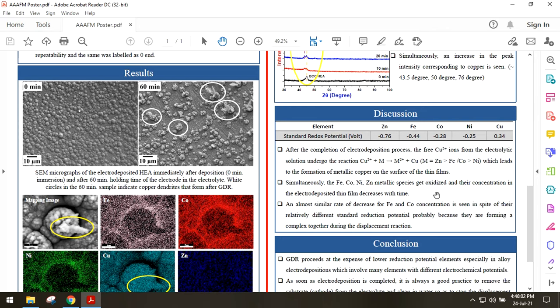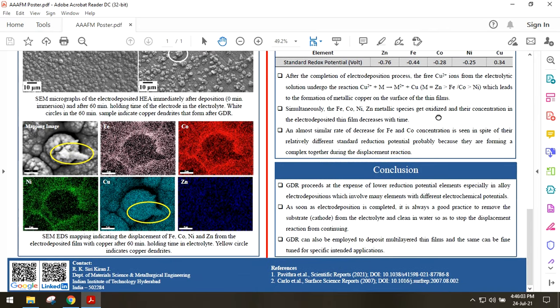Placing the electrode in deionized water right after the electrodeposition can eliminate GDR. Though GDR reactions are unwanted reactions, they can still be employed to form ABB-type multilayers where A is an alloy and B is copper respectively.